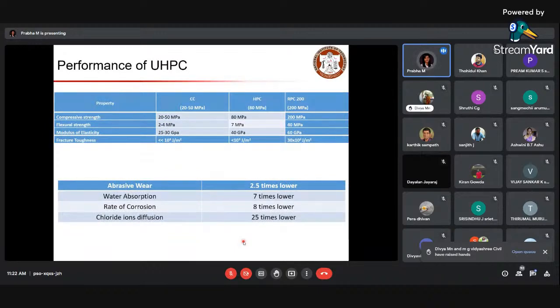So when you talk about the performance of ultra high performance concrete, you can see this is a control mix, and you have a high performance concrete in the range of 80 MPa. This is about 200 MPa. The compressive strength is significantly high for this RPC, which basically indicates reactive powder concrete, which is one form of this ultra high performance concrete. The fracture toughness is also significantly high.